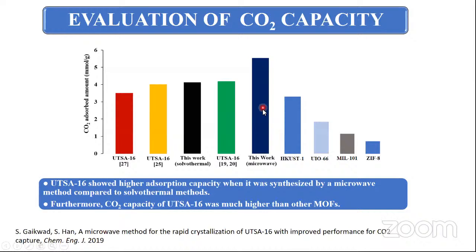This is our good achievement: we reduced the time from 48 hours to 4 hours, and the CO2 absorption performance of our material is better than previously reported UTSA 16 cobalt made by the solvothermal method.